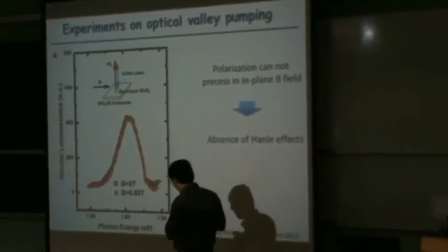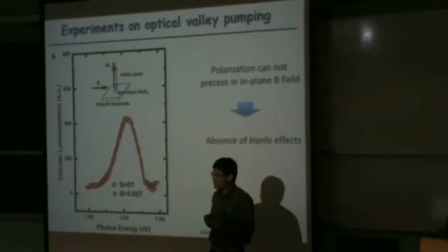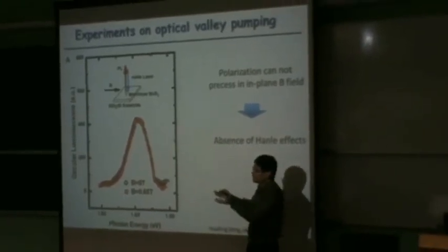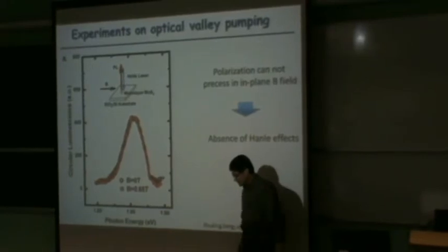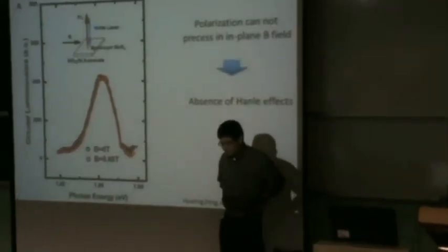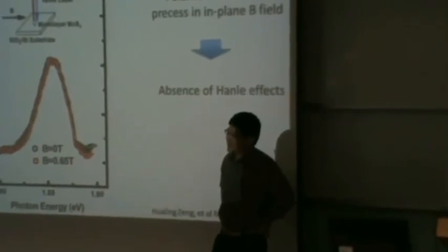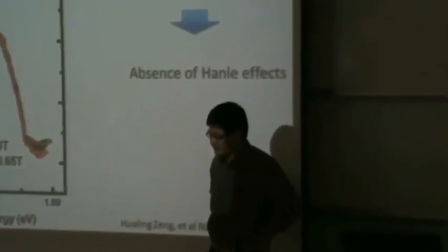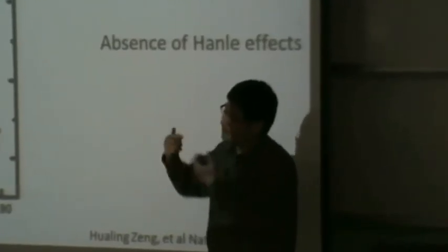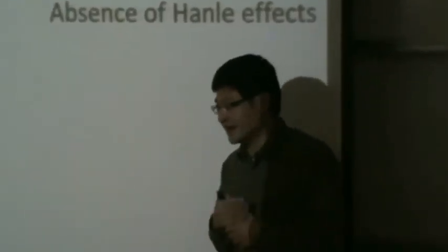We supposed in the beginning we wanted to check the g factors, and also to see if we can kill the polarization. Unfortunately, with fields up to 2 tesla, we didn't see anything. There could be something, because the spin and also the orbital momentum possibly cancel each other. I cannot see the exact story here. Possibly Wang Yao can give some calculation. But on the experimental side, we didn't see any effect, at least at the 2 tesla level. And that's pretty much the limit we can reach.